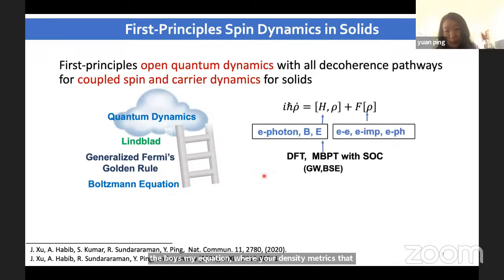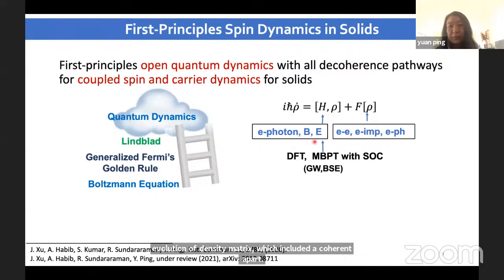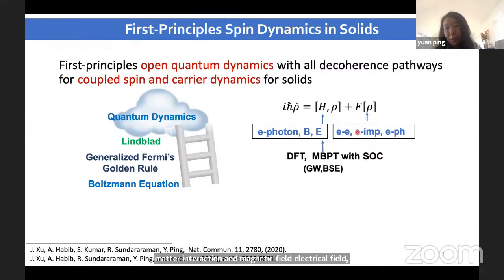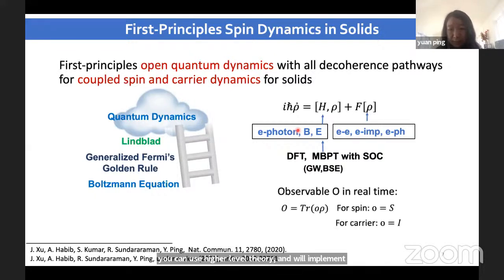And at the end, if you treat it semi-classically, you recover the Boltzmann equation, where your density matrix becomes a diagonal occupation number. So we do the time evolution of the density matrix, which includes the coherent part, where you have the light-matter interaction, magnetic field, the electric field, and the scattering part, including the scattering due to electron-electron, electron-impurity, and electron-phonon with spin-orbit coupling. The input states can come from DFT, or you can use higher level theory. And we implemented this in the interaction picture, where we put the electron correlation in the H0, basically static. And we compute the observable by taking the trace of the density matrix with a spin operator or carrier.